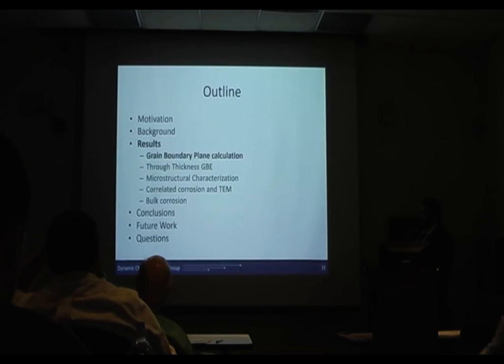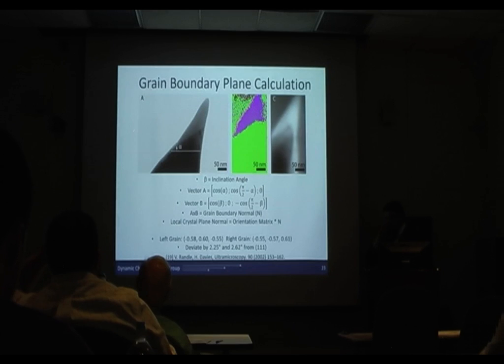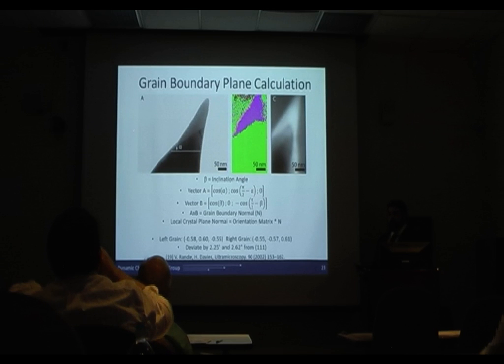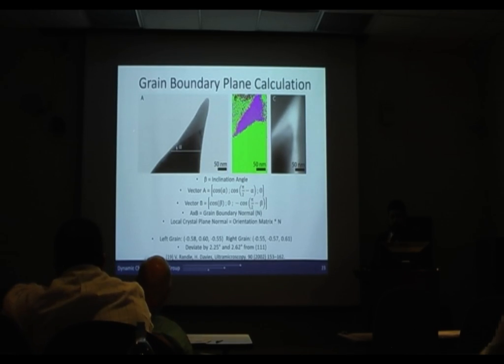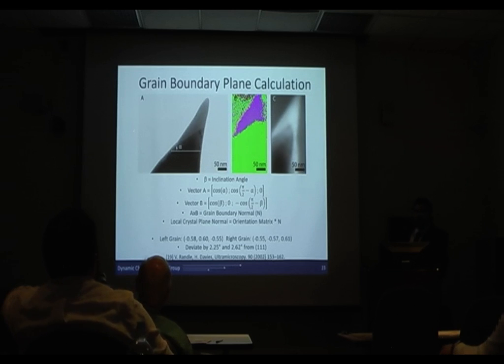So moving on to my results. First question was calculating the grain boundary plane. There are established methods for doing this in TEM, but initially we wanted to do atom probe tomography and correlate that with the grain boundary plane. However, the problem with that is the specimens for that don't load well into a standard double tilt holder. We do have a dedicated holder for them for TEM. However, it only has a single rotation axis, which makes typical analysis somewhat more difficult.